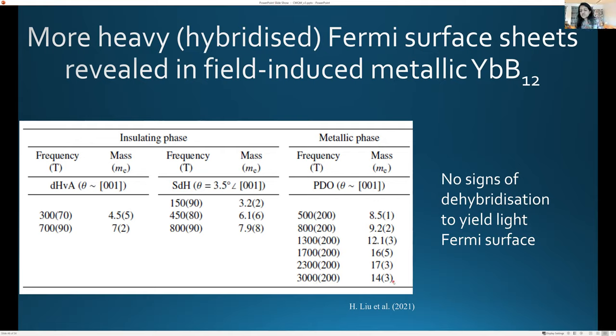I don't think I've shown it here, but I suppose I should have. I can show you that the value of gamma in heat capacity rises dramatically from about 5 to about 50 on either side. So in the insulating phase, it's about 5, and in the metallic phase, it's about 50. So it seems like it is acquiring more heavy Fermi surface sheets as it goes into the metallic phase.